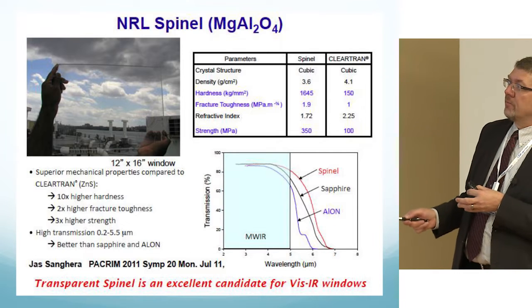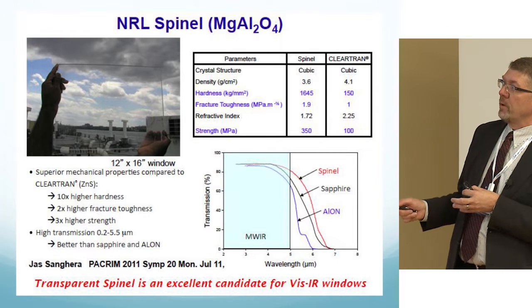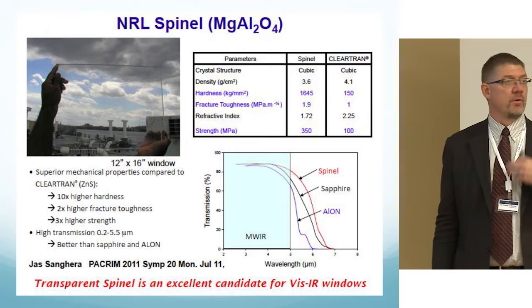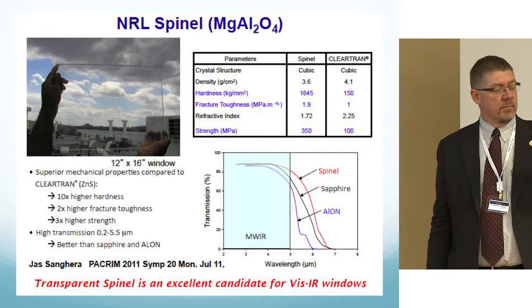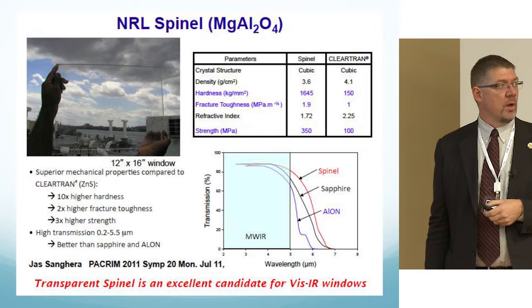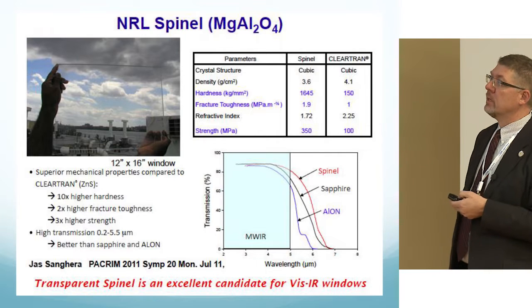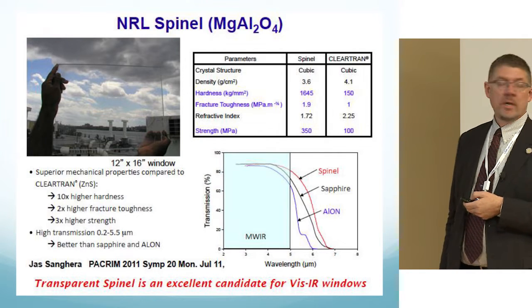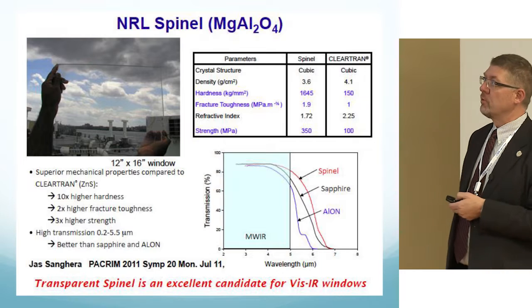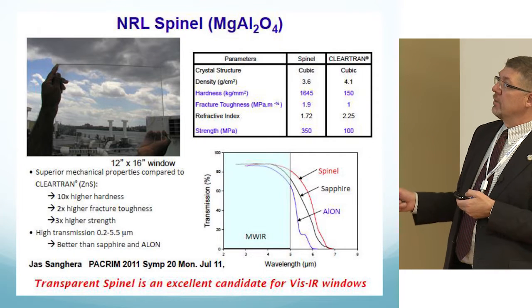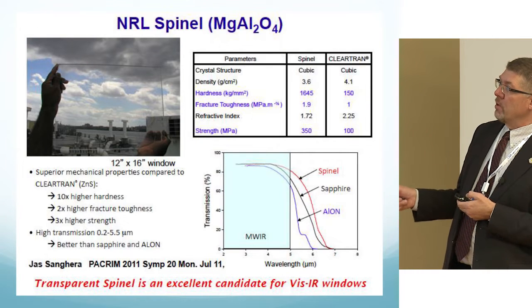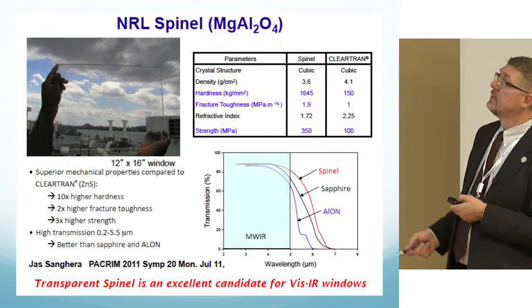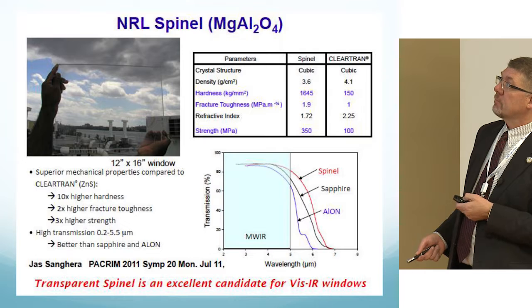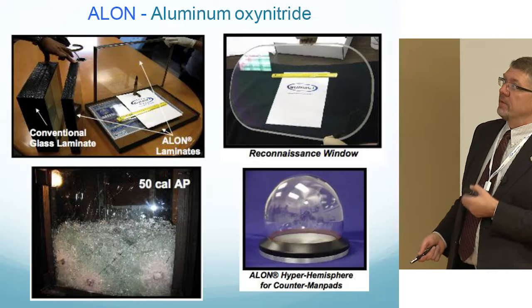Well, it's got a fairly nice visible transmission window here as well as mid-wave. So for doing FLIR from aircraft, for doing windows for armored personnel type of devices, it's a good high quality material with an extremely good amount of strength. You can see here that the spinel does show better mid-wave transmission than both aluminum oxynitride and sapphire. And this kind of highlights it from a different perspective.